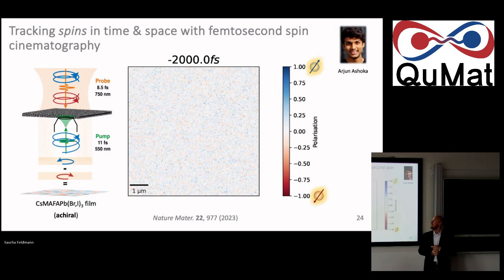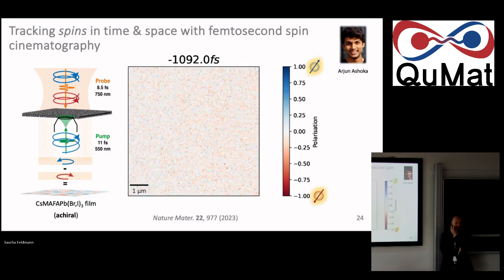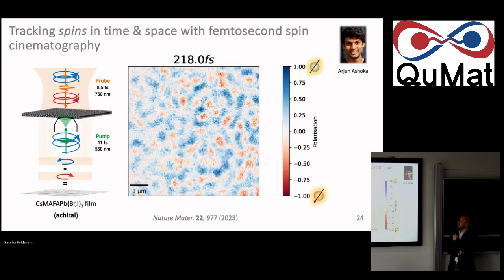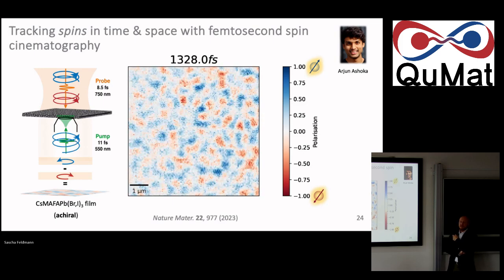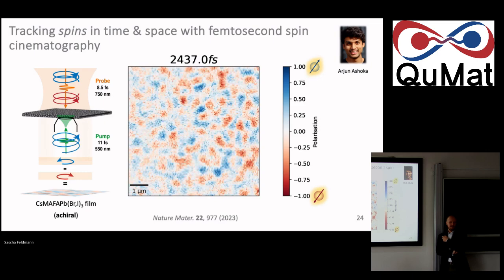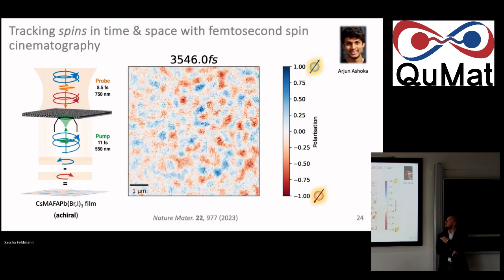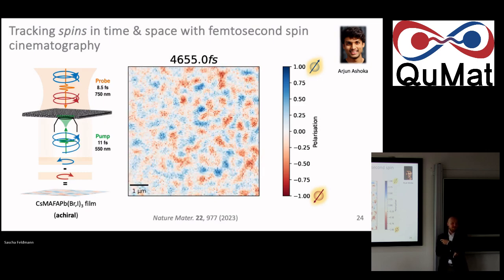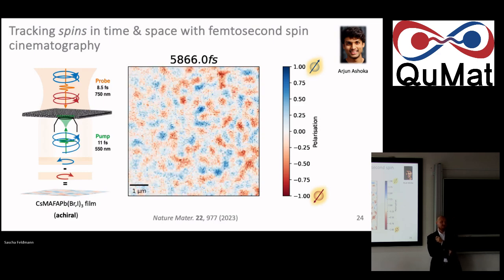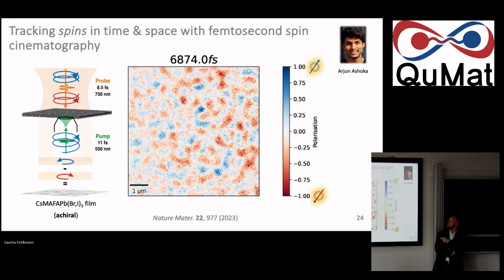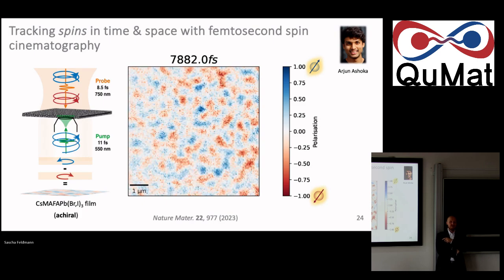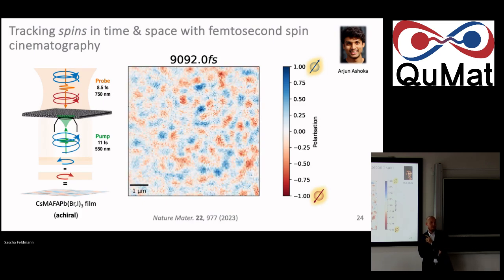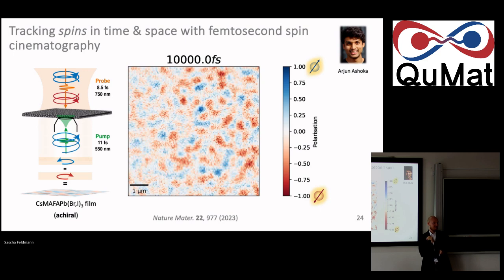Okay, so let's do that. And at time 0, the pump hits. And what we find is, rather unexpectedly, this strong formation of these different domains that are positive or even negative in polarization, and that outlast this measurement for quite a while. We are now talking 7, 8 picoseconds in. Remember, I spoke about 2 or 3 picoseconds max in the past for the bulk measurement. So this is very curious and unexpected. So let's try to understand how can this come about.